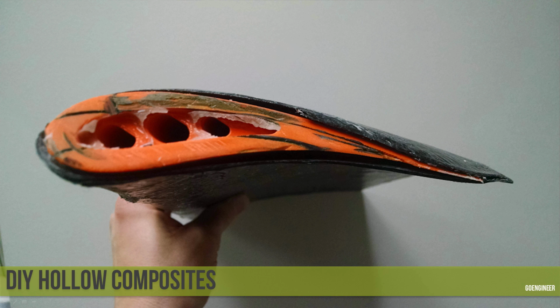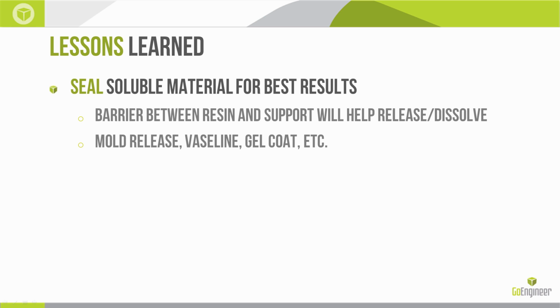Embedding parts that are printed is a little bit difficult. As far as the water soluble portion, that wasn't adhered to the outer skin, for my own fault, it worked great. So, to recap the lessons learned here: definitely seal your soluble material for best results. You need to have a barrier between the resin and the support material, and that's going to help it release and dissolve. And again, that might be mold release or gel coat or something like that.